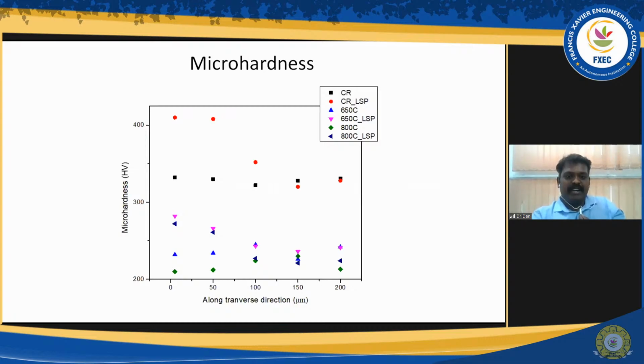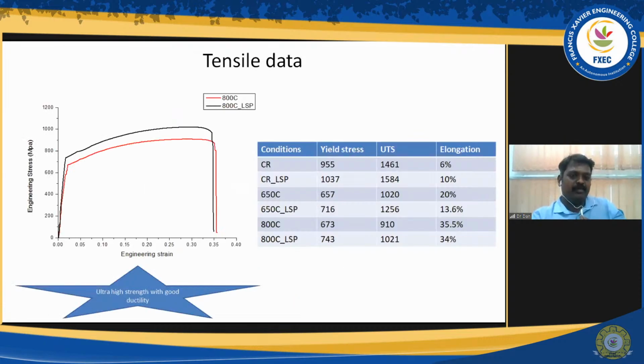For micro hardness, after the LSP process you can see an increment in the hardness near the surface, but if you go inside the material, there is no significant enhancement. In the tensile test, I could see a significant enhancement in strength after LSP. The ductility is also not affected in the case of the 800-degree sample, but in the case of 650, the strength is really high and the ductility is reduced a little bit, about 13% after LSP.